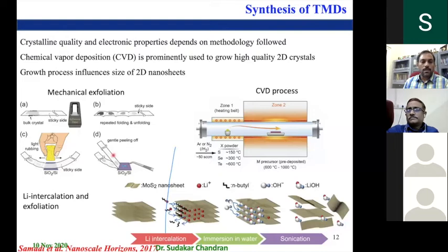But the disadvantage of this technique is you don't get anything beyond a few tens of microns, maybe 100 microns, nothing beyond that. So if you want it for applications, you should be able to grow them over a large area. So the CVD process is one of the processes in which you can grow large area crystals. Of course, a lot of process optimization is required. That itself is a deep research that is going on.